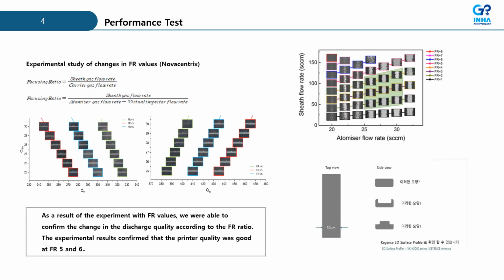We conducted an experiment to find the usable line width section by controlling FR, sheath gas, and atomized flow, and also found a method to control the side view. The FR value is the ratio of the flow rate of aerosol entering the nozzle and the flow rate of sheath gas. As a result of the experiment with the FR value, we were able to confirm the change in the discharge quality according to the FR ratio. The experimental results confirmed that the printing quality was good at FR 5 and 6.